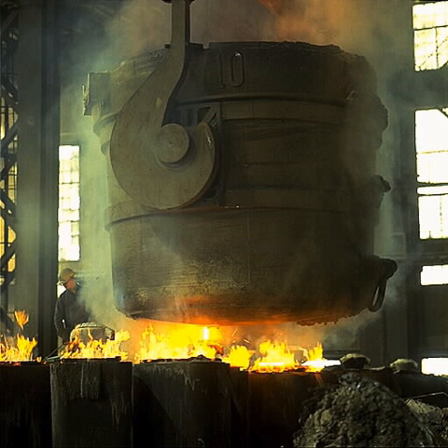The above assumes that the cooling process is very slow, allowing enough time for the carbon to migrate. As the rate of cooling is increased, the carbon will have less time to migrate to form carbide at the grain boundaries but will have increasingly large amounts of pearlite of a finer and finer structure within the grains. Hence the carbide is more widely dispersed and acts to prevent slip of defects within those grains, resulting in hardening of the steel. At the very high cooling rates produced by quenching, the carbon has no time to migrate but is locked within the face-centered austenite and forms martensite.